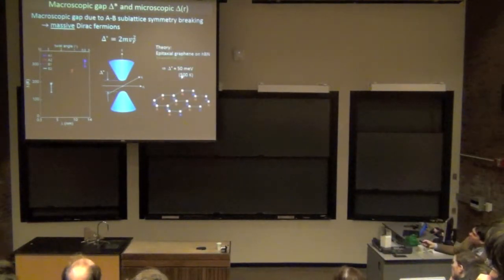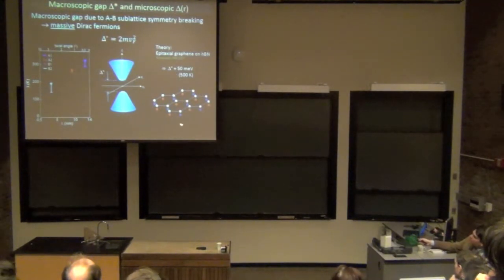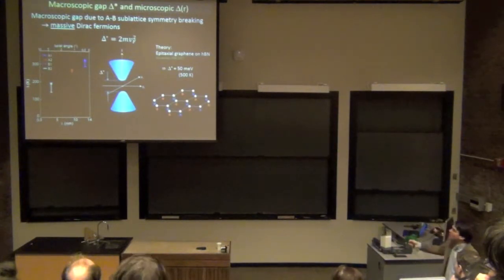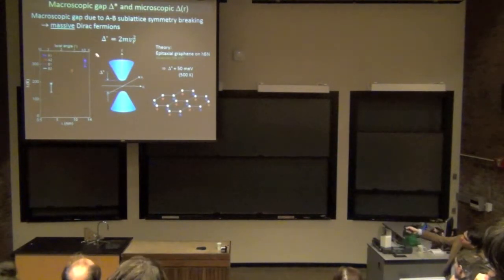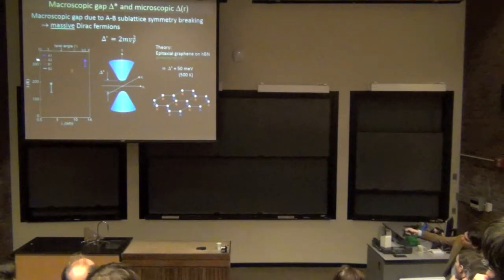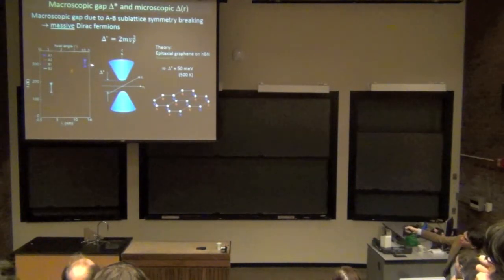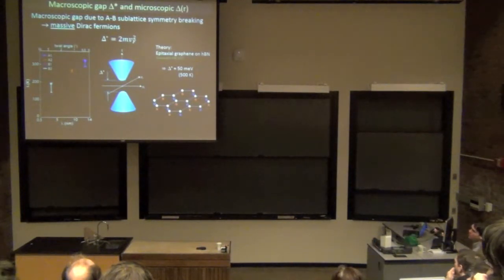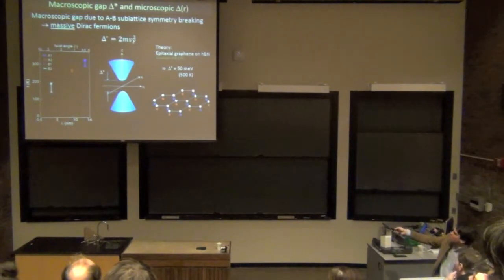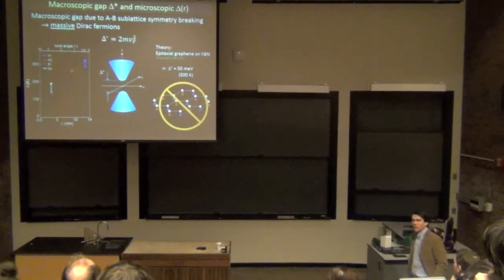So if we go back to that theory that I showed you before, it predicts this epitaxial structure should have a gap that's roughly 50 millivolts, which is close to what we see. It's actually up here. We measure about 30 millivolts for the lowest twist angle that we have in the system. This picture can't be right, though.